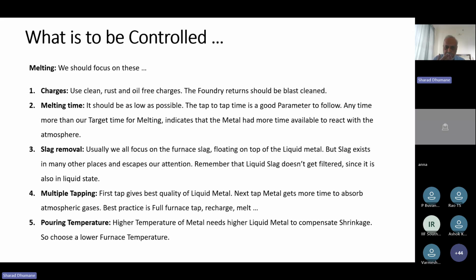Multiple tapping. The best quality metal is from the first tap. So if you are able to tap all of your metal into a ladle in a single tap, that gives you the best quality of liquid metal. But if there are multiple taps, then the first ladle goes and comes back, and during that time your metal is on hold, so the melt quality slightly deteriorates. So as far as possible, go for one single tap.